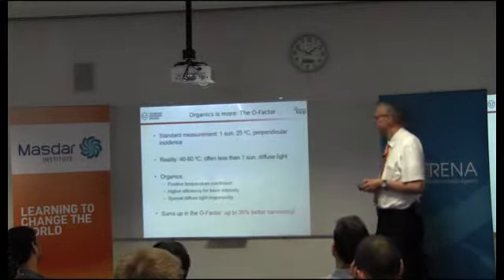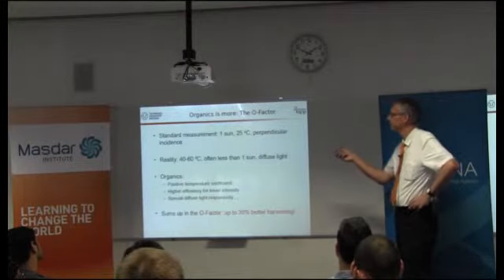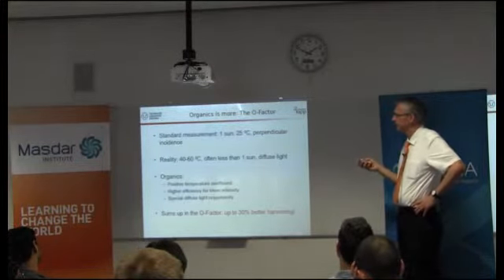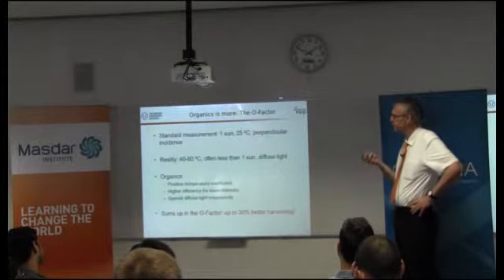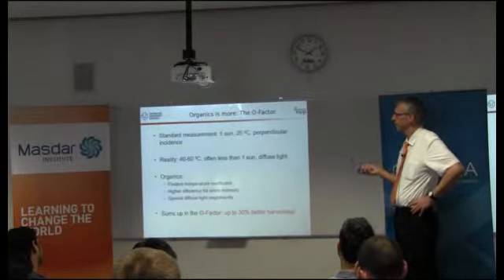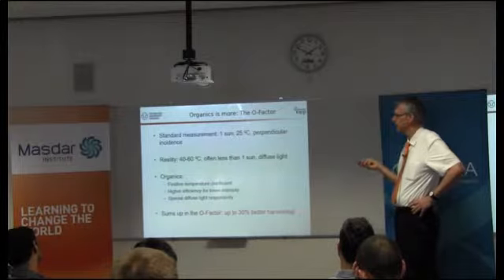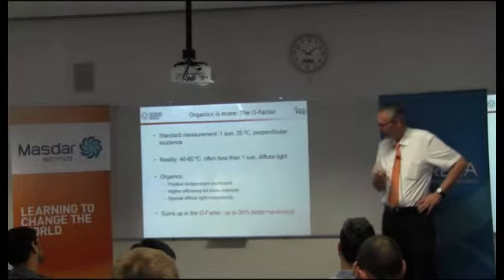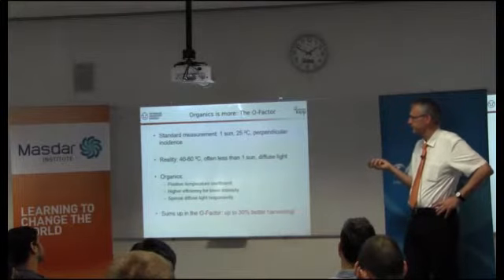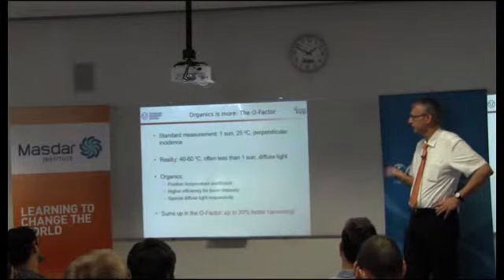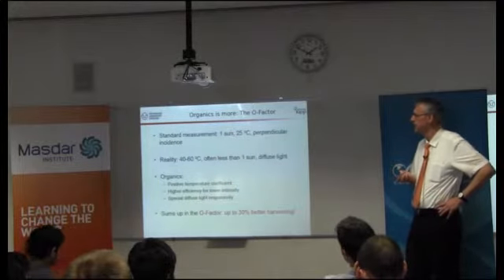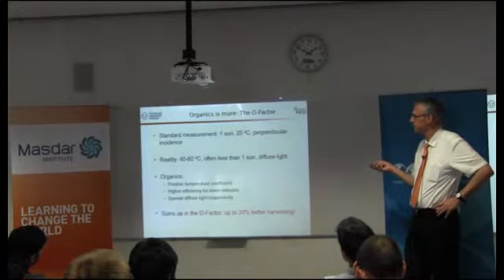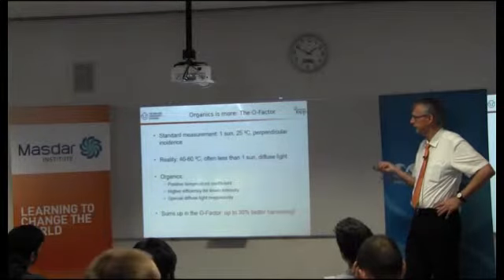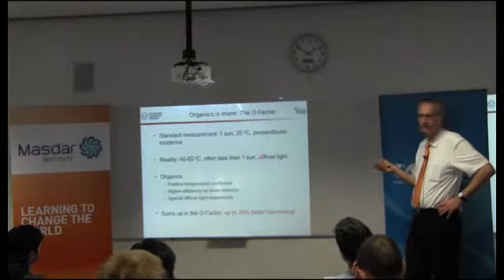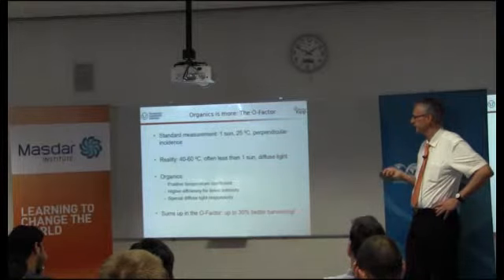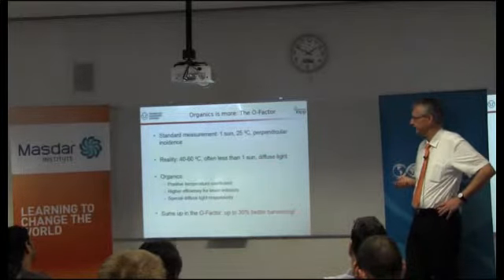Now, why do I say that 12% is better than it sounds? It's something we call the O factor, and the reason is quite simple. When you quote an efficiency in photovoltaics, you quote the standard measurement, which means one sun, 25 degrees and perpendicular incidence. Especially in a country like Abu Dhabi, this is not the case. In reality, outdoors you have 40 to 60 or even more degrees. At least in the morning and the evening, even on a sunny day, you have less than one sun. And if there's haze, as there often is in these desert countries, or clouds, then you have diffuse light.